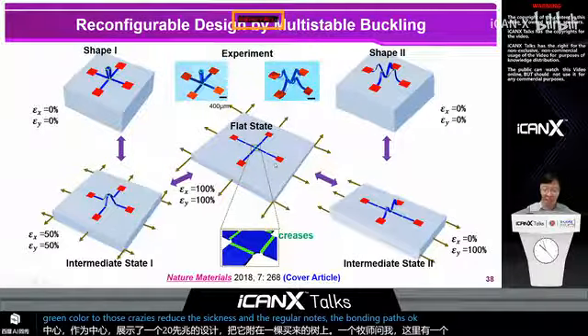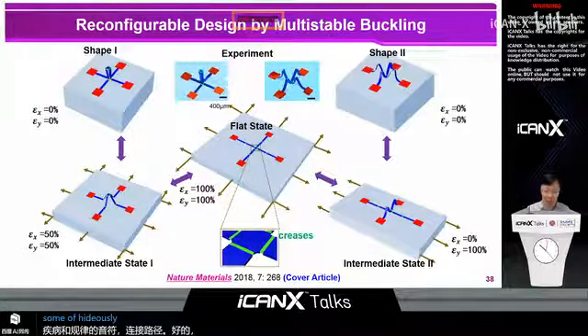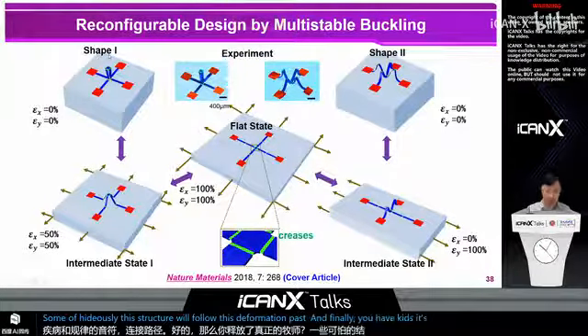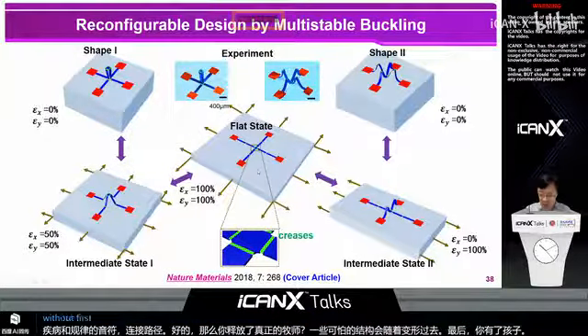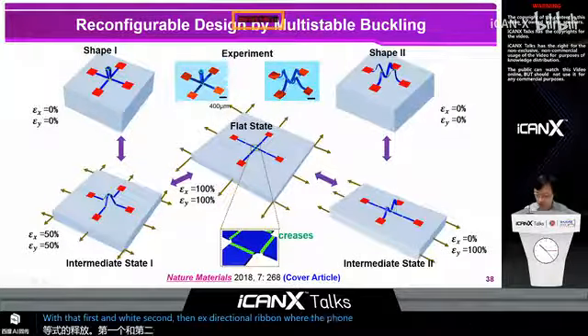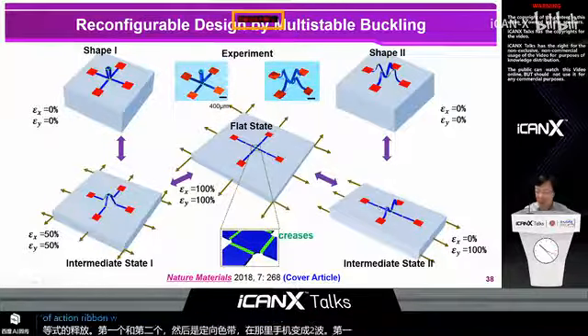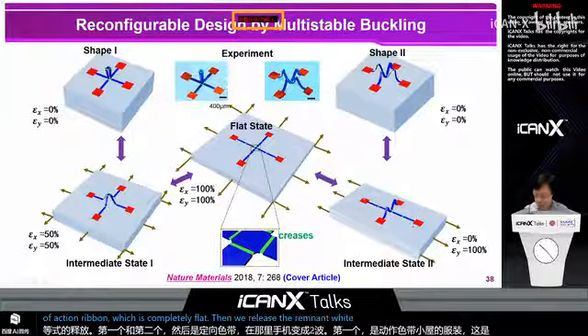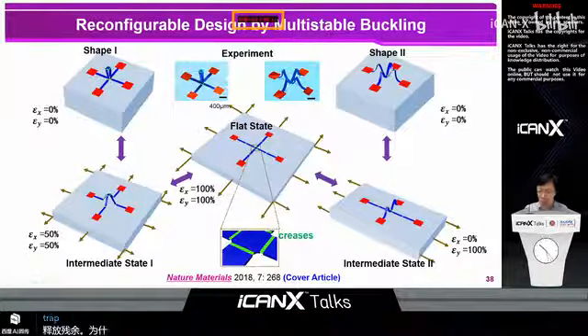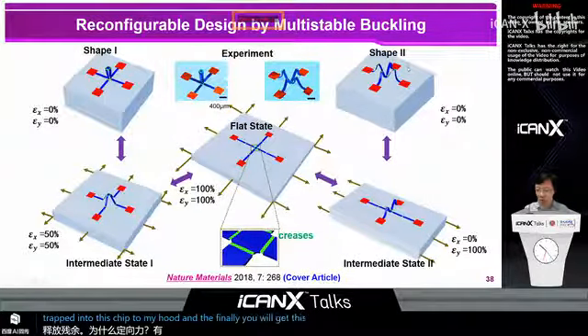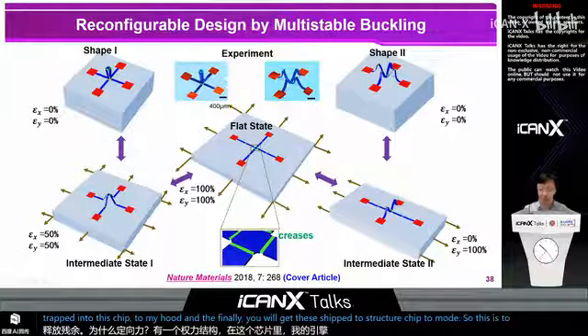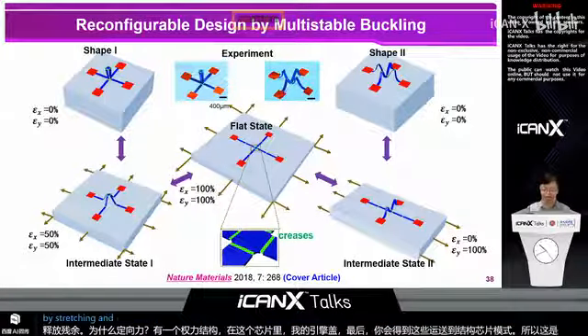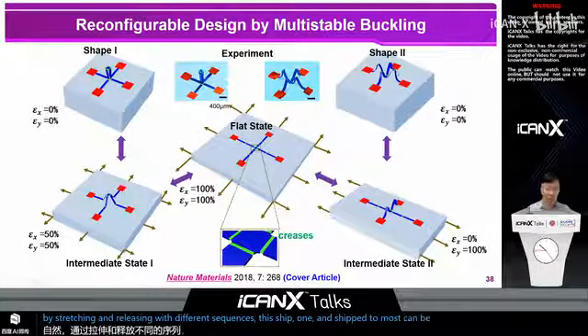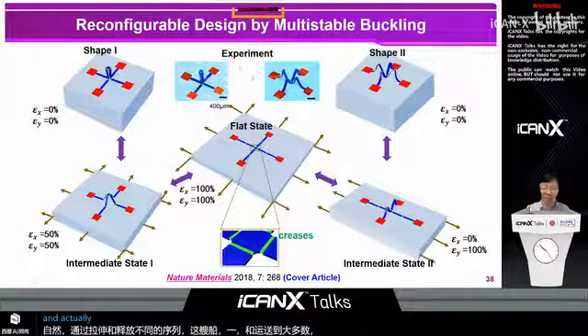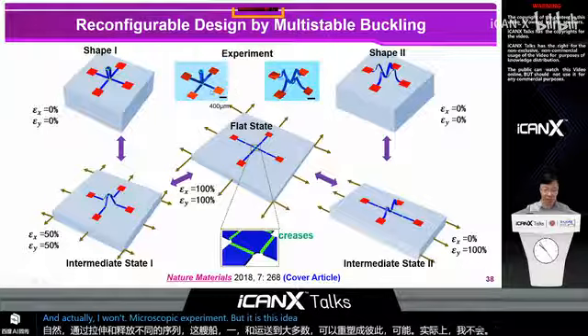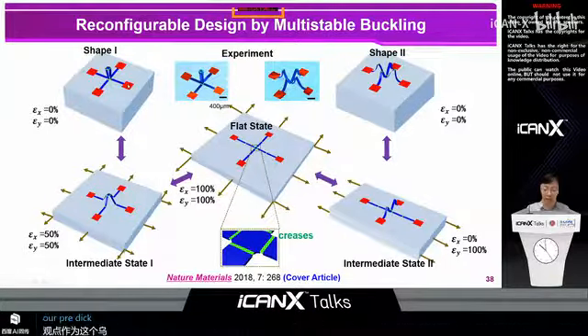Okay, so when you release the biaxial pre-strain simultaneously, this structure will follow this deformation path, and finally you will get this shape 1 mode. But when you do sequential release with X first and Y second, then this X directional ribbon will deform into 2 waves first because of the constraint from the Y directional ribbon, which is completely flat. Then when you release the remnant Y directional pre-strain, then the entire structure will be trapped into this shape 2 mode. So this is a 2-wave mode. And actually, by stretching and releasing with different sequences, this shape 1 and shape 2 modes can be reshaped into each other reversibly. And actually, our microscopic experiment validates this idea, as evidenced by this good agreement between our experiments and our predictions of the 3D configurations.